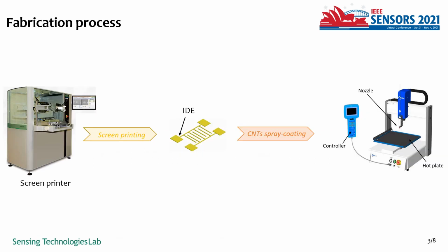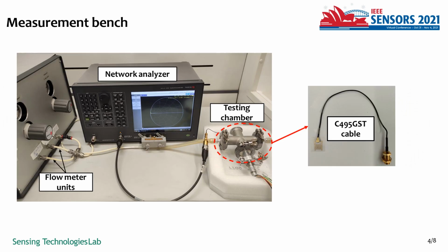So here we have the fabrication process of the gas sensor, where the interdigitated electrodes were screen printed using silver ink, and then the carbon nanotube water-based solution, which was used as a sensing material, was spray coated using a spray coater. And here we have the measurement setup where we have the flow meters to control the flow of ammonia and nitrogen, which is used as the carrier gas. And then we have the testing chamber where the ammonia gas sensor was exposed to ammonia. And also we have the network analyzer.